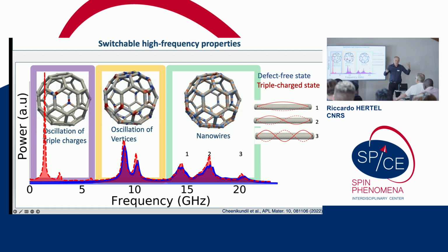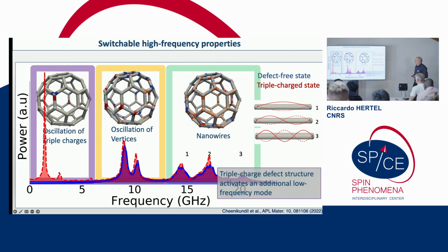And if we have one that contains these 2 defects that I was talking about before, then they provide an additional, if you want, fingerprint in the Magnonic spectrum, a rather large absorption peak that develops at low frequencies when they're present. So by following the recipe that I said before of removing and inserting these defects, we can introduce or remove this peak and thereby manipulate the Magnonic response of the system.